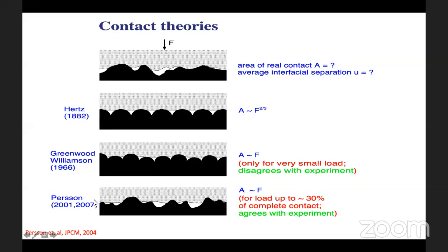In 2001, Persson introduced what is called multi-scale contact mechanics, in which he found that the area of real contact is approximately proportional to the force, but for high loads. So the difference between Greenwood-Williamson and Persson's theory is that Persson's theory agrees with experiments, because here the relationship between area and normal load is valid up to 30% of the complete contact.